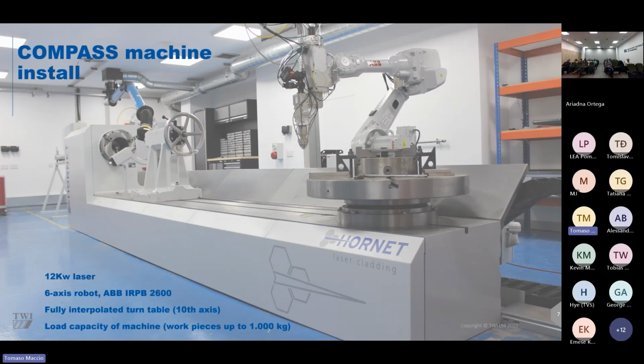We've also installed a fully interpolated turntable that's been very useful for doing samples and geometries. It has a load capacity of 1,000 kg, which is useful for the pipelines that we can add in. This is just a feasibility study at the moment, so it's not the full length of the machine. We're not able yet to clad the full 12 meters on this machine. We could clad 4 meters externally, and 4 to 5 meters if we rotate the component around. It's just for the initial feasibility study of doing the cladding within this work package.